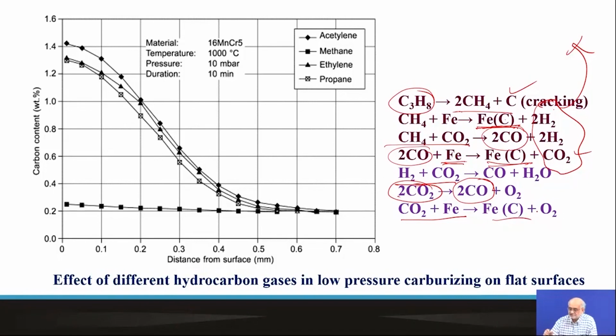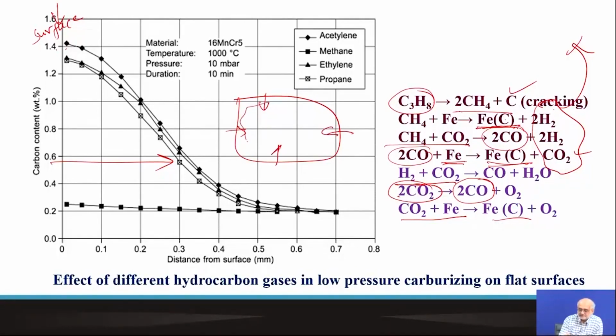So the case depth or the carbon enrichment from the surface, so this is the surface, and this is how we are going below the surface. So this is the component, and this is how carbon is diffusing in and is creating a case on all sides with a certain depth. And typically in any direction from the surface, let's say in this part, this is how the carbon profile looks. So it's highest at the surface and gradually decreases. So we have to set our goal that we want, for example, 0.8% enrichment or 0.9% enrichment. Then we are talking about, this is the typical depth, so about 0.3, 0.4 millimeter. But the overall carbon enrichment can go to higher distance or higher depth from the surface.